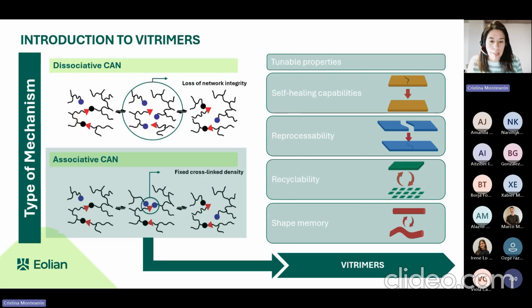So dynamic polymer networks can be classified into two main types, depending on their interaction mechanism: dissociative CANs and associative ones. In a dissociative CAN, the covalent bonds break before the new ones form. This leads to a temporary loss of network integrity, causing the material to behave more like a viscous liquid when the exchange is activated. In contrast, associative CANs follow an exchange mechanism where a new bond forms at the same time that the old one breaks. This means that the material keeps a constant cross-link density, preserving its network structure even during bond exchange.